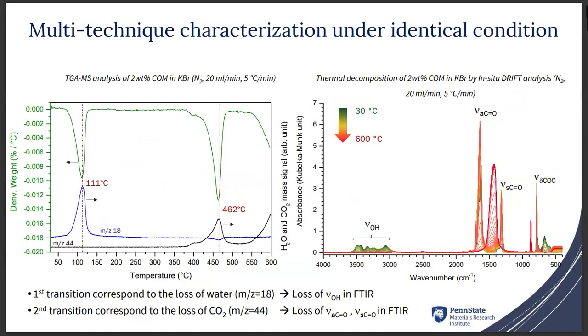Then we tried to compare, under the same conditions, the TGA-MS, so we could confirm that the first event corresponds to the loss of water by looking at mass 18. The second event corresponds to the loss of carbon dioxide, recorded using mass 44.